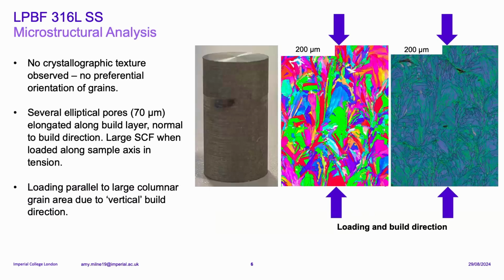So I started off by doing some microstructural analysis on the untested samples, and this was sliced vertically down that way. No crystallographic texture was observed, and so there was no preferential orientation of the grains. You can see several elliptical pores on here, about 70 micrometers in length, and they're elongated along the build layer. So in compression, these are likely to be closed, but in tension, there's a chance that these can create a large stress concentration factor and reduce the performance of the part.